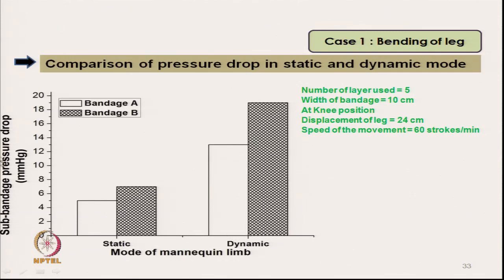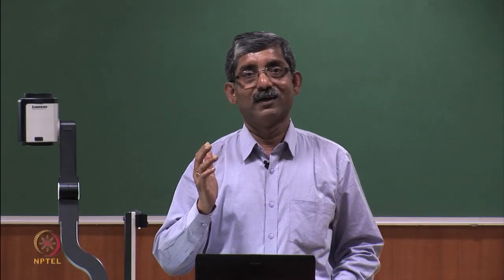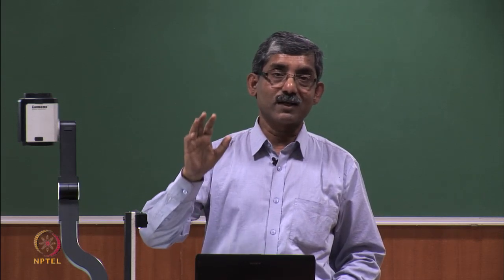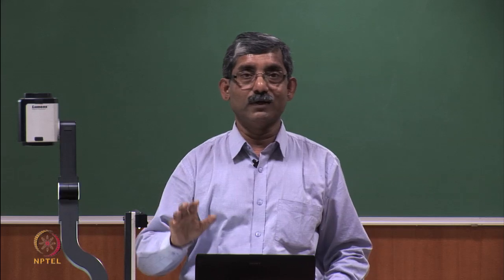This is the drop in pressure. If you see in static mode, both for bandage A and B, the pressure drop is least, which is required. But once the person is dynamic, the pressure drop is much higher, which means after putting on the bandage, if a person moves, the pressure drop will be high, that means the reduction in pressure of the compression bandage will be high.